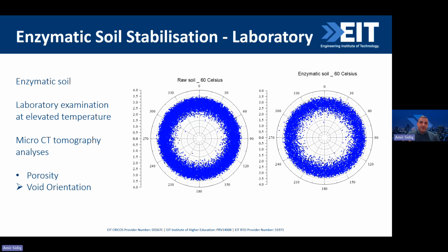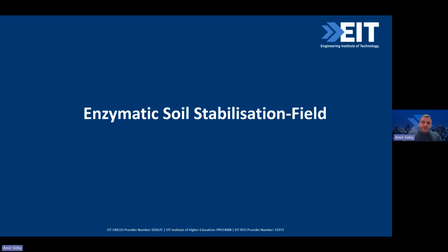As I mentioned in my first slide, the shape of the clay, or the distribution of the clay particles, will actually vary. By using something like this enzyme material, it controls this variation, which is controlling the swelling and the shrinkage, so we have the structure stabilized, not experiencing these different mechanisms downward or upward. So we have a good understanding of this material at laboratory scale, then moving to the field.